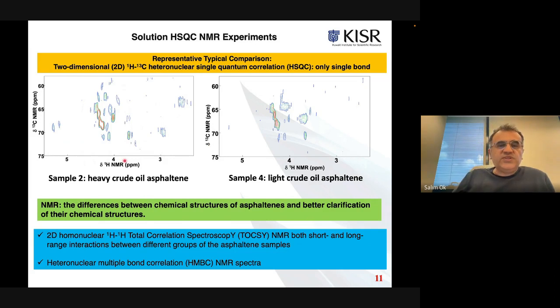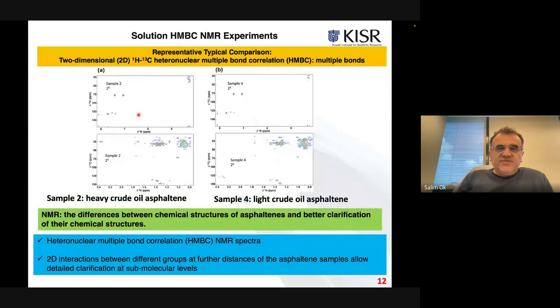When we switch from one sample to another and zoom into the same region, we can see differences - for example, certain correlations don't exist in the spectrum of sample 2, and so on. When we conducted HMBC experiments, we gained even further information, because HMBC also tells us about longer range distance interactions between different protons and carbon-13.